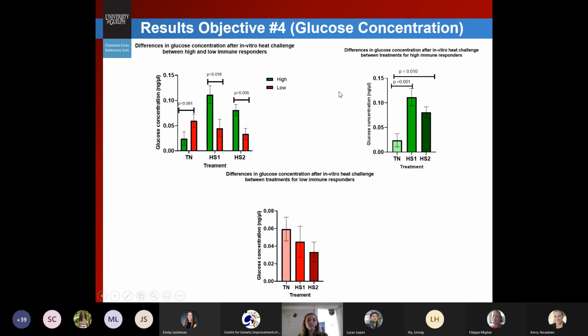So these first few graphs show our results for glucose concentration. This first graph shows the comparison between the phenotypes within each heat treatment. At thermoneutral, we found that our low responders had a trend towards greater glucose production compared to our high immune responders, possibly indicating already at thermoneutral that those low responders are using the glycolysis cycle versus oxidative phosphorylation.